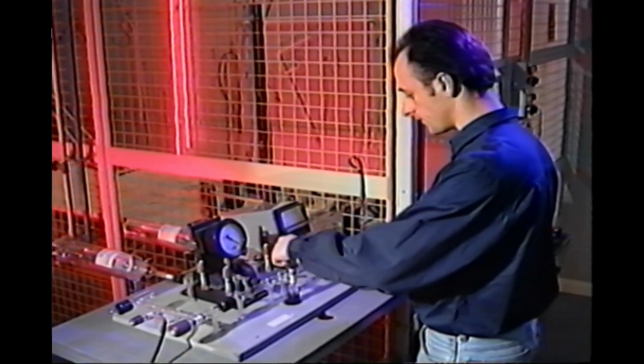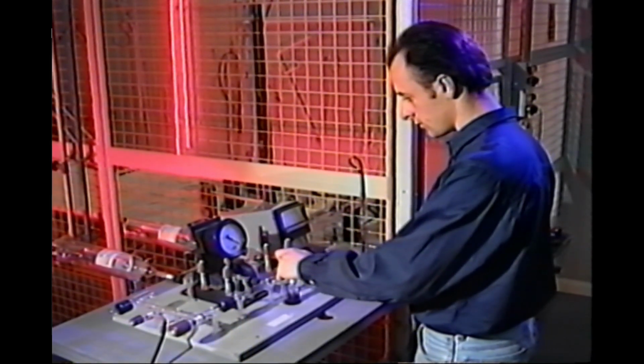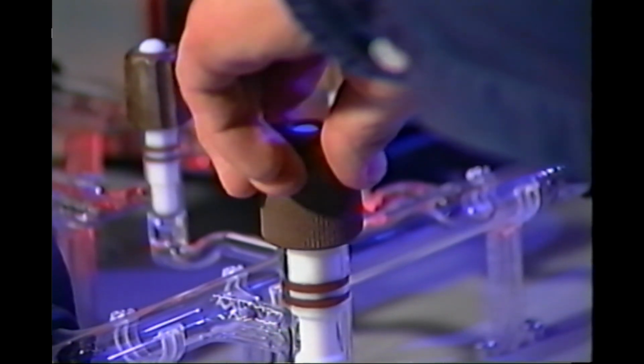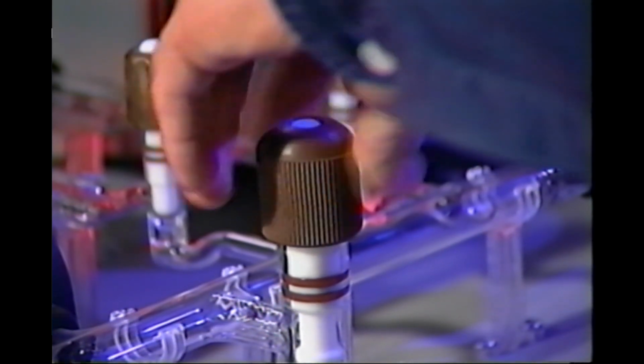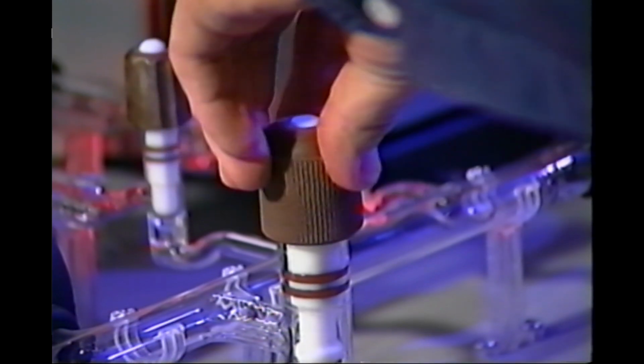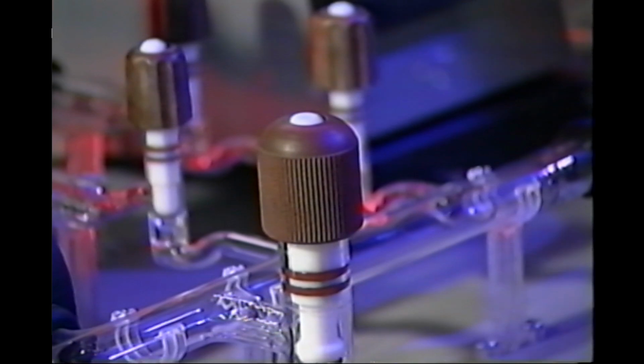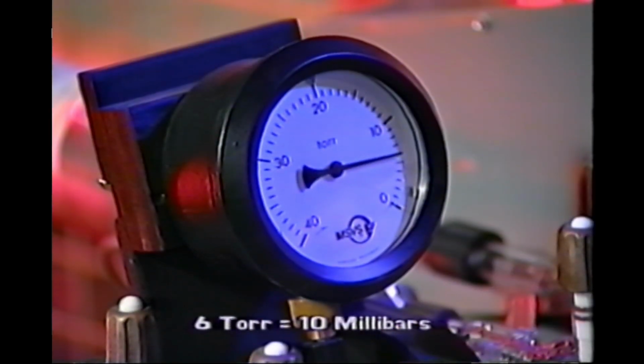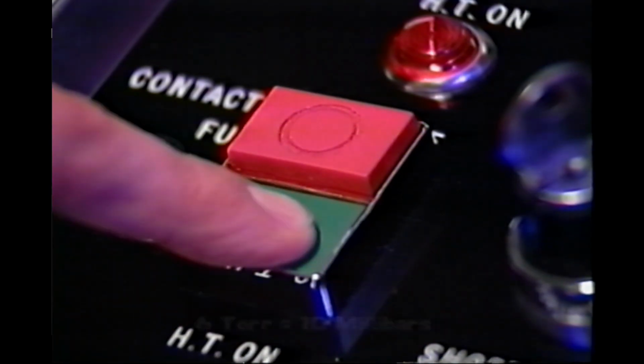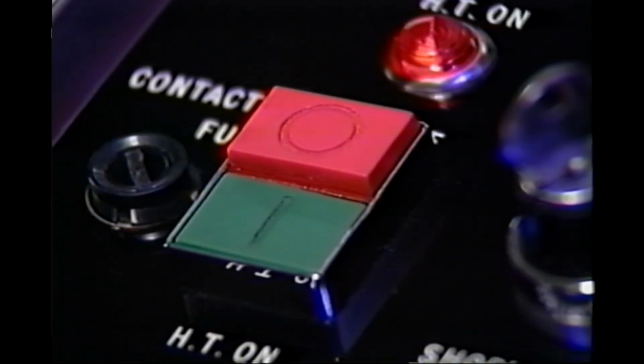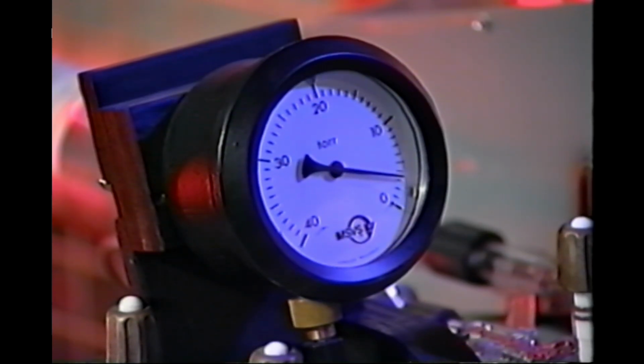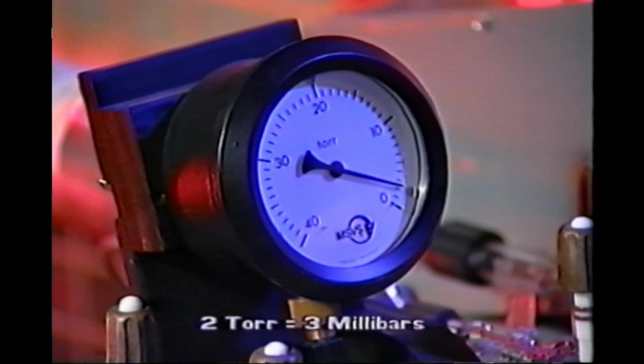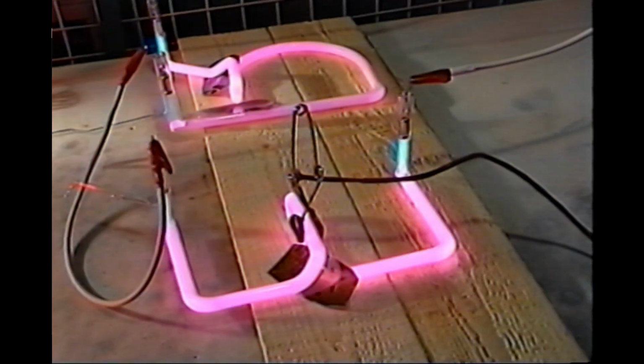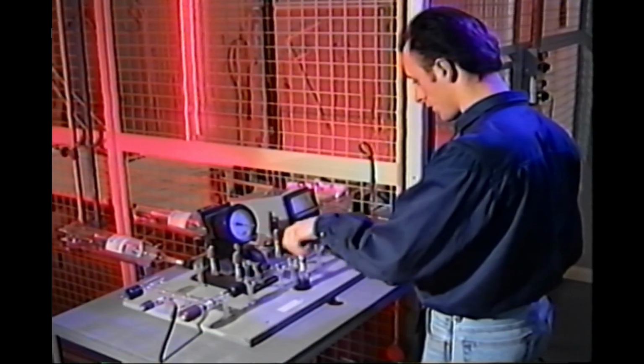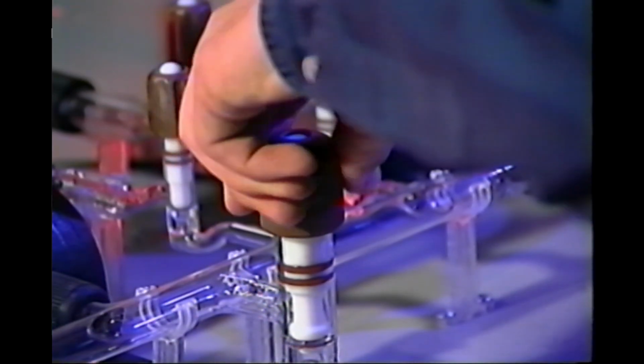The bombarding stage of processing can now commence. Open the main stopcock slowly to allow the pumps to begin evacuating the tubes. When the tube pressure falls to 6 torr, registered here on the capsule dial gauge, switch on the current. Allow the pressure to continue falling, and at around 2 torr, the tubes will strike up. At this point, close the main stopcock.